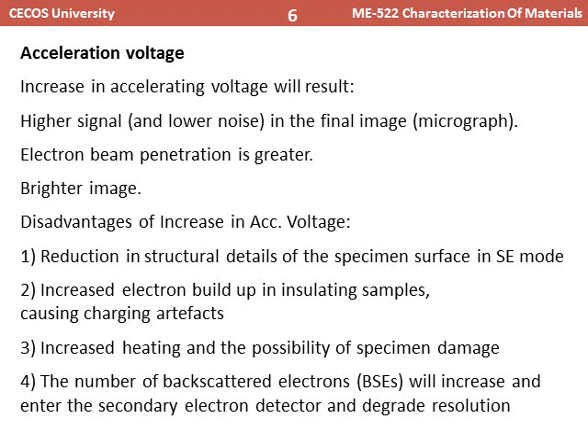However, this accelerating voltage is not always beneficial. It has some disadvantages as well. By increasing the accelerating voltage, we are reducing the structure details of the specimen surface in the case of secondary electron mode. As you know, most of the images acquired by scanning electron microscopy that are reported in the literature are acquired by the secondary electron mode.